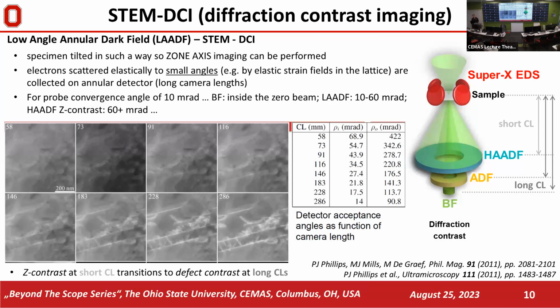I'll start now with so-called low-angle annular dark field diffraction contrast in STEM. So we tilt our crystal into zone axis, and we focus on creating an image and creating contrast using exclusively elastically scattered electrons to low angles. So we work with either a bright field detector or an annular dark field detector, and we form the image. As you can see, here is an example of how just simply changing the camera length, changing the type of electrons which we are collecting on our detector and the type of electrons which are creating our image, we can heavily affect the visibility of our defects.